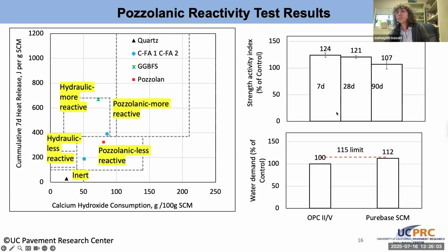Then you can see we run strength activity index and report the percentages relative to the control, which is 100% cement, and all of these other ones have 20% replacement of cement with that SCM, in this case, pure base SCM. We want those generally to be, according to the standard, higher than 75%. We look for 80%, generally keep an eye on 7-day and 28-day together, or look at the 90-day. If either one of them passes, it is a very good indicator we're not getting a filler effect or false positive, and that the material is good and reactive. We also keep an eye on water demand, making sure that all of those capillary pores that want to suck water from the concrete, we fill them up, and the material is happy with the amount of water it has received, and that we can incorporate it into concrete.